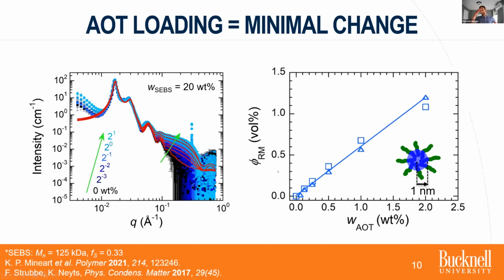Now, when I get to talking about diffusion, one of the parameters that will be important that we don't actually measure here, but we take from literature, is the hydrodynamic radius of these reverse micelles, which has been determined in a couple of different publications to be right around 1.7 nanometers. And so now we kind of have a fuller picture of the structure of these things in our gels. Other than that, there's not a lot of exciting things happening here. We're basically adding more AOT reverse micelles as we increase the AOT concentration.